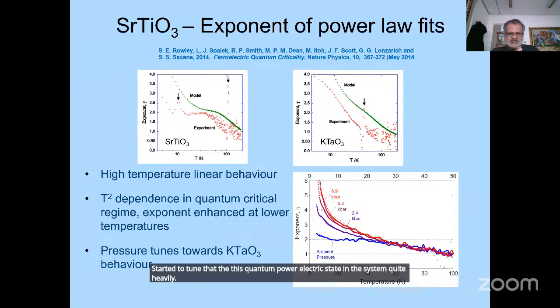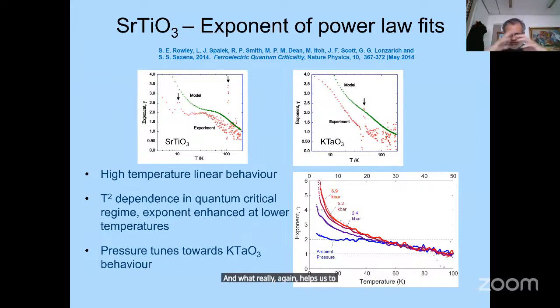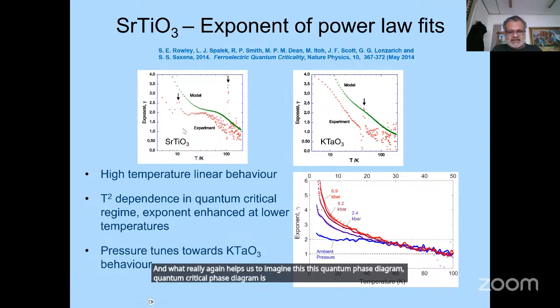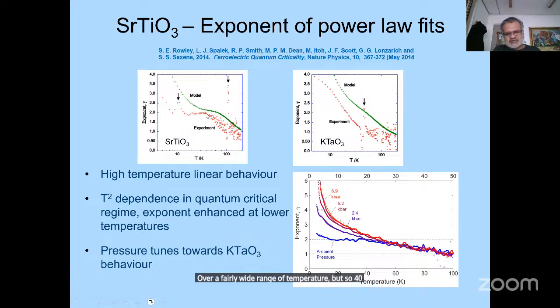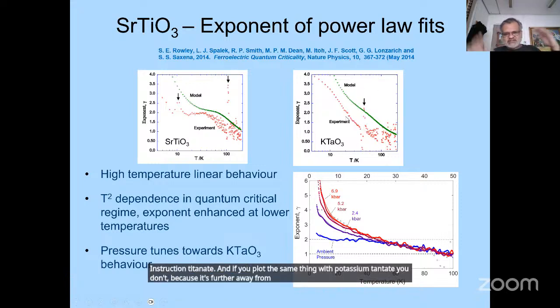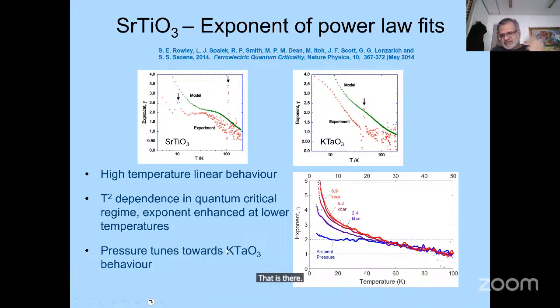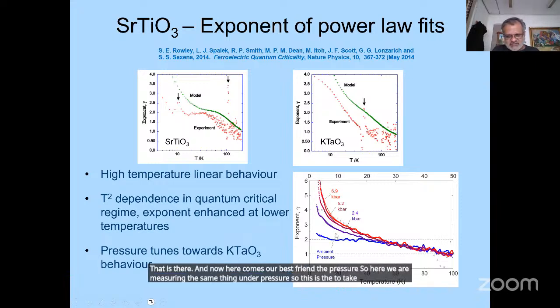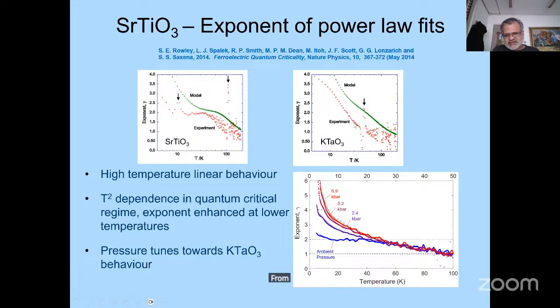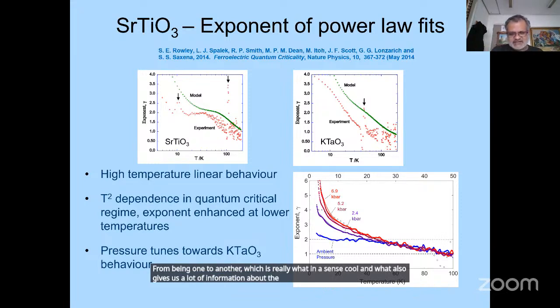What again helps us imagine this quantum critical phase diagram is the T-squared exponent, which is plotted over a fairly wide temperature range of 2 to 40 Kelvin in strontium titanate. If you plot the same thing for potassium tantalate, because it's further away from the critical point, you don't find that stable area. And now here comes our best friend, the pressure. Here we are measuring the same thing under pressure. You take the same set of exponents at ambient pressure, then start applying pressure, and you can see how it goes from being STO to KTO. You can actually push this material from one to the other, which is cool but also gives us a lot of information about the nature of couplings in this material.